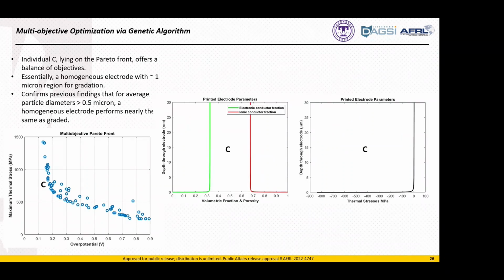And interestingly enough, individual C here is kind of a balance of objectives. And you can see it's just a homogeneous electrode where the electronic conductor fraction has been minimized down to what's called its percolation threshold. So the minimum fraction at which you can get particles chained together and able to conduct electricity all the way through.